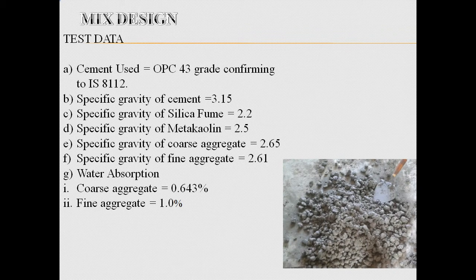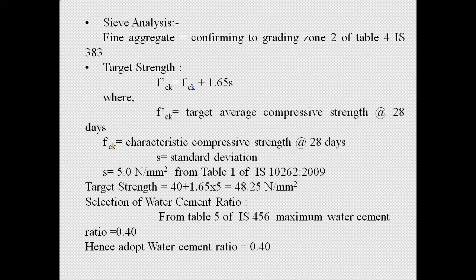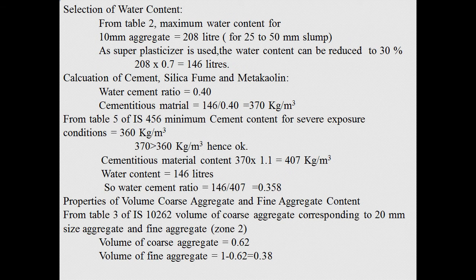And here is our concrete mix, which is mixed after the sieve analysis, and target strength is based on the formula fck plus 1.65 s, where s is the standard deviation, which is taken as 5 for M40 in Table 1 of IS 10262. So therefore the target strength is 48.25 Newton per mm square for M40, and hence we have adopted a water cement ratio of 0.40, and selection of cementitious material based on the water content of 146 is 370 kg per meter cube,